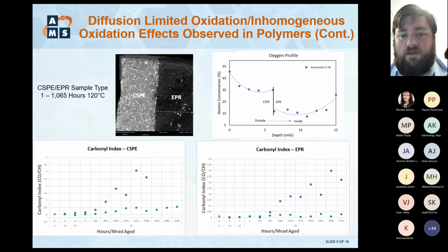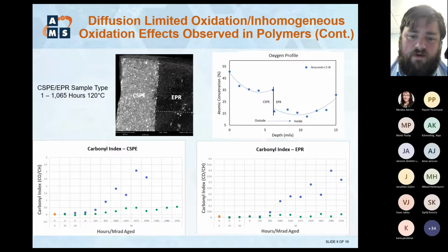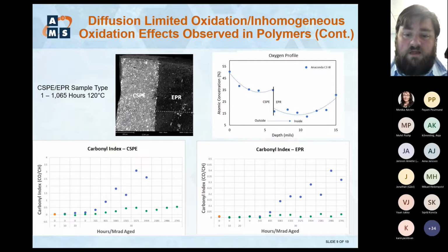Similarly, you can actually see the EPR when it starts finally changing in the type 1 material, and you can see its oxidation levels or carbonyl index changes are significantly behind the Hypalon layer because of DLO effects in the type 1s. But also the EPR in the type 2s and 3s are represented by the green data points. There's been very little change in carbonyl index or levels of oxidation observed in those materials up to 2,745 hours. So these are the kind of differences we've observed in the materials and the different types of aging phenomena and effects we've seen from a diffusion limited oxidation standpoint.